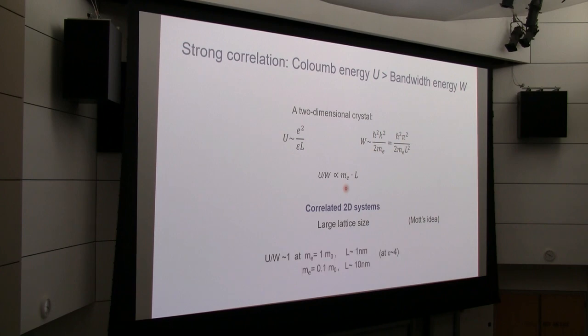If we put in the numbers, we can ask, how large a lattice size you need. So if you have electron mass that's 1 of rest mass of electron, you need a lattice size about 1 nanometer, when we assume dielectric constant of 4, which is dielectric constant of boron nitride. And if you have an effective mass of 0.1, then you need a lattice size about 10 nanometer. So as you can see, this argument is actually rather simple. It's just considering the potential energy versus effectively kinetic energy.